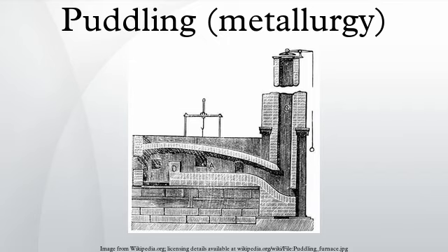This process causes the slag to puff up on top, giving the rabble a visual indication of the progress of the combustion. As the carbon burns off, the melting temperature of the mixture rises from 1150 degrees Celsius to 1540 degrees Celsius, so the furnace has to be continually fed during this process. The melting point increases since the carbon atoms within the mixture act as a solute in solution, which lowers the melting point of the iron mixture.